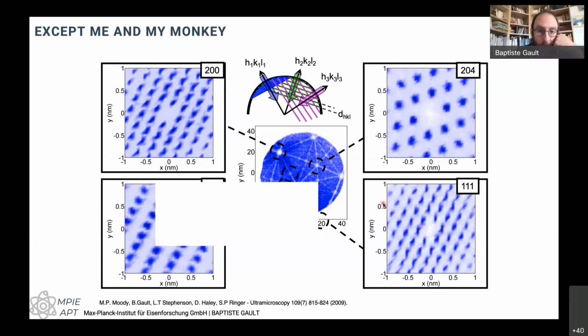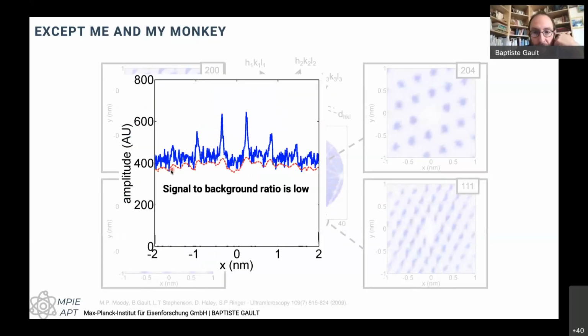The thing is, if I take a slice through one of these maps, I can see that there are very, very few of the atoms that are reconstructed properly. Most of them are in the background somewhere. So laterally, we are losing the interatomic distances, but in Z, we are reconstructing them properly. So this is information that is really quite important to bear in mind when we analyze data, and when you guys might encounter atom probe data sometimes in papers.